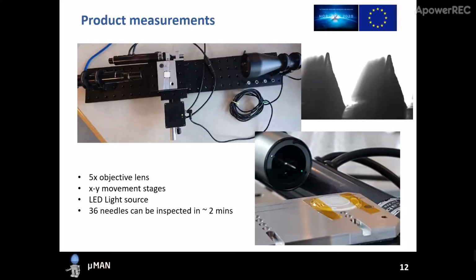After manufacturing our parts, we cut them and use this telecentric optical measurement apparatus for quality inspection. So we use a 5x objective lens on the left hand side here, and we have X and Y movement stages which could move automatically and which could be controlled by LabVIEW based software. And we have an LED light source on the right hand side, which is a telecentric illuminator, and 36 needles can be inspected in approximately 2 minutes, and it's a very useful tool for assessing the micro replication quality of our parts. And this is a telecentric image of the microneedles, as you can see on the top right.